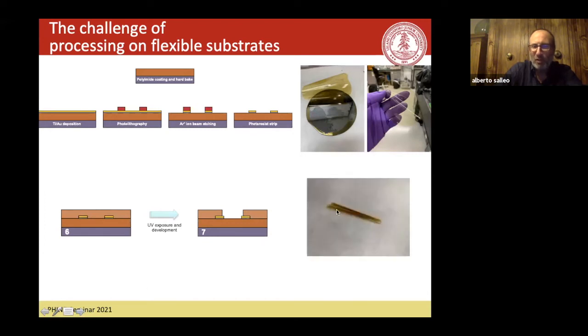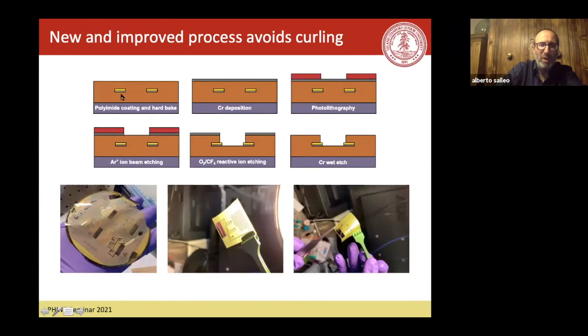Once we did that, actually it was even worse, because this polymer, which was different so they could be photo-defined, had a different thermal expansion coefficient from the polyimide, and so this curled it even more, because now rather than just having two small metal lines, we had a whole layer on top that made it curl. And so the solution, as you can imagine, is to use the same polymer top and bottom. So we developed a recipe to use polyimide top and bottom.